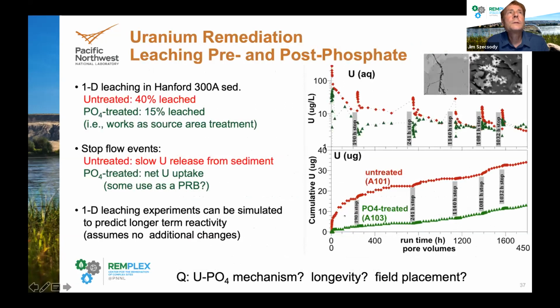So first of all, just why are we using phosphate? This is the "it works" slide. So shown on the right side here are two column experiment results in the lab. The red one is untreated and the green one is treated. This goes for about 450 pore volumes, or it was about 6 months long. So quite a few pore volumes of water were flowed through there. The uranium concentration, I put on a log scale, so it kind of compresses the high concentration a bit, but I did that for a reason. But if you look at the cumulative uranium leaching out of the sediment, you can see that there's a considerable difference between untreated and treated. So about 2/3 of the uranium was sequestered by treating the sediment with phosphate.